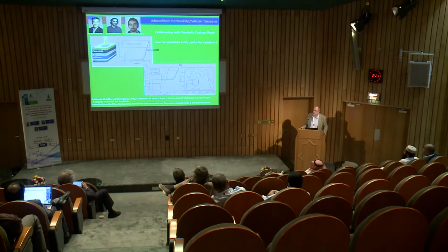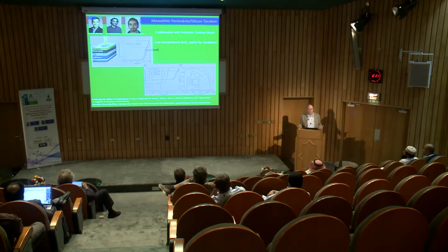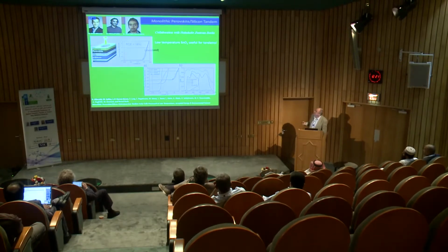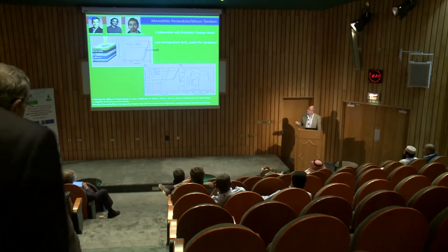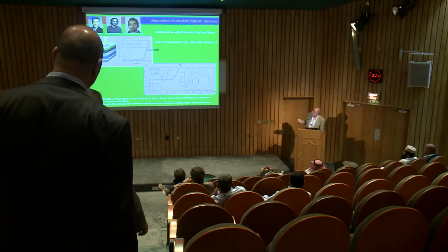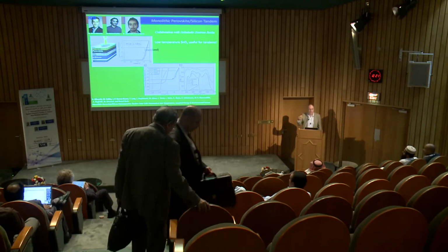This cell is done at moderate temperature, so we can think about using them for flexible substrates. We don't need more than, let's say, 150 degrees Celsius. One initiative was to collaborate with a group in Berlin who works with silicon solar cells, to make a monolithic tandem cell. So you basically take a silicon cell, add on the layers of tin oxide, perovskite, and then make a tandem cell device. And the idea here is, of course, that you can get higher efficiency than a one-cell absorber.